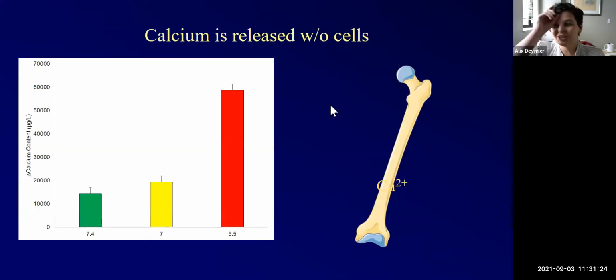What a surprise. Just like the in vivo system, we're also releasing calcium. So the behavior does seem to be very similar. And you can see that the amount of calcium that was leached out of the bones and into the solution is correlated to the pH. So as I have a lower pH, more calcium is being taken out of the bone and into the solution. So we're going to do the same thing. Let's go ahead and do some Raman and see what happens.